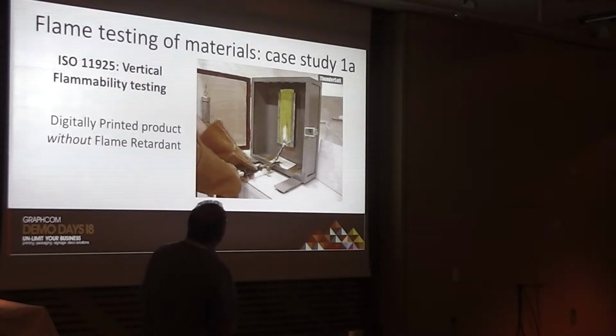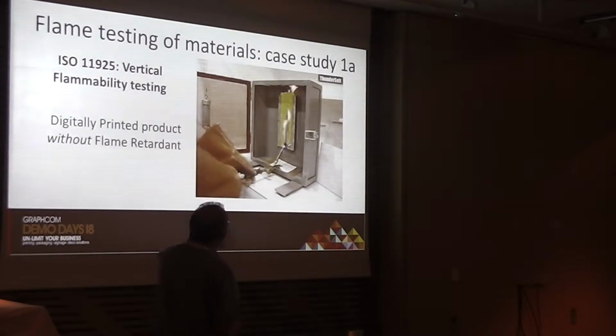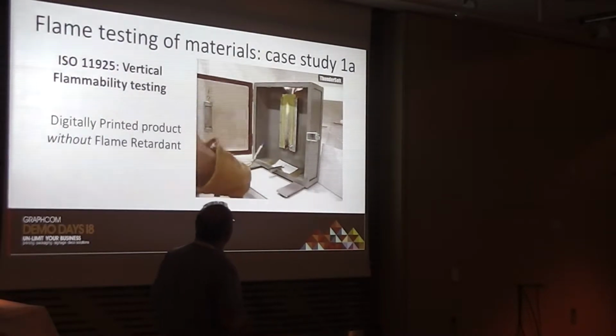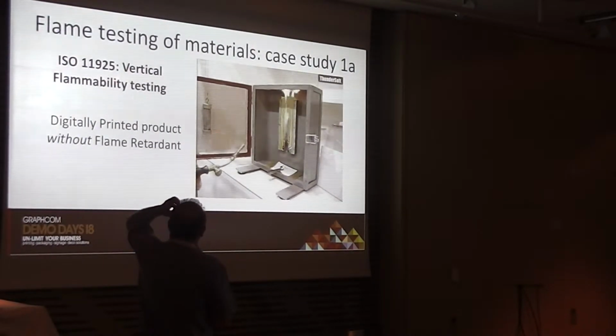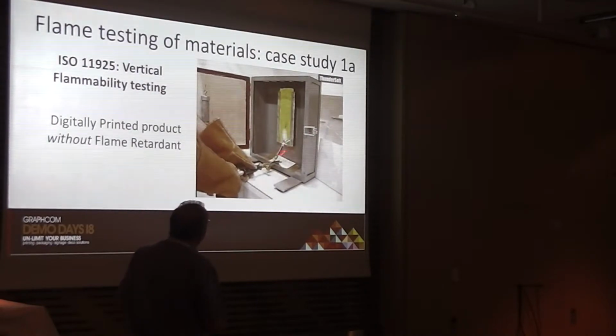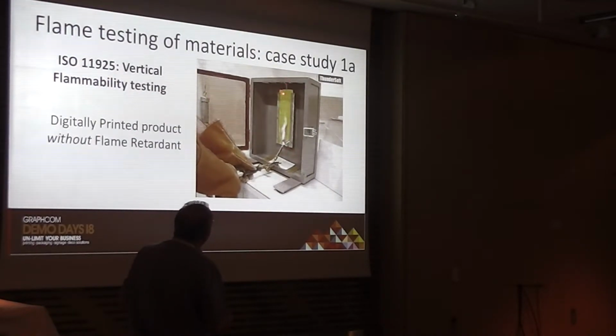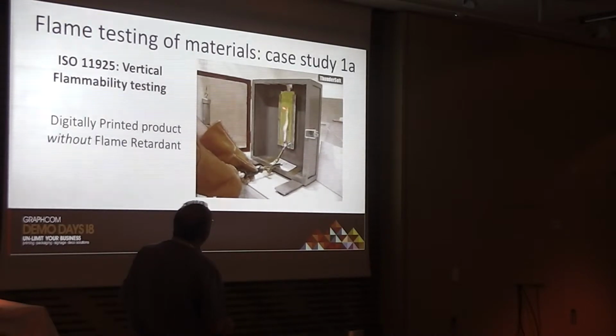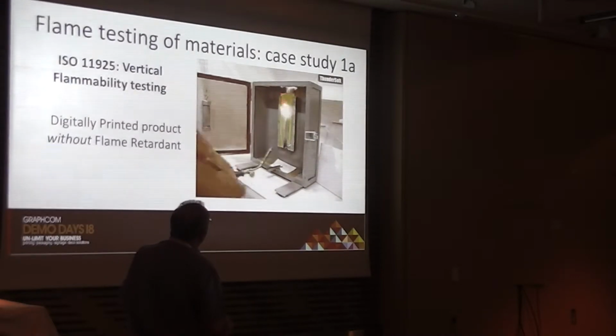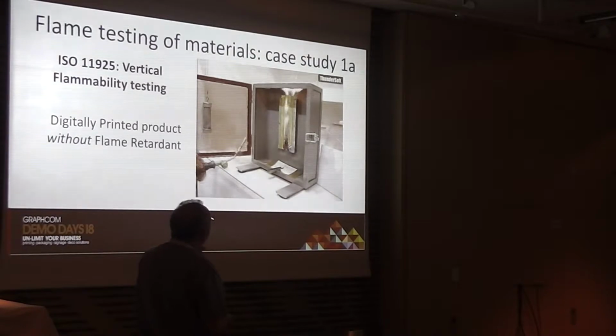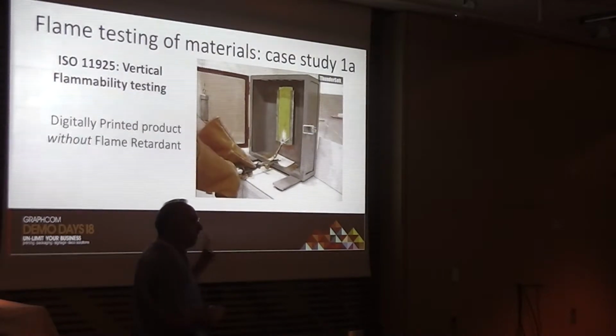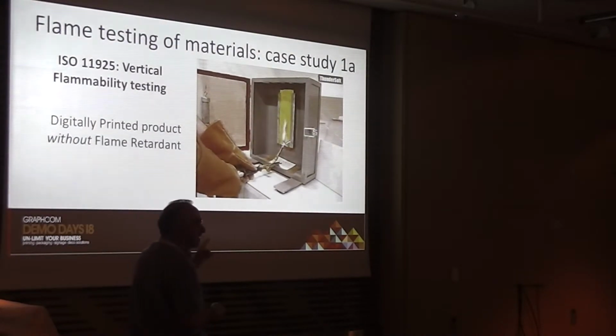This one here is a little GIF that shows it without flame retardant. It's actually a card that we did some work on some time ago. This is according to 11925. And you can see that the flame is already from behind and it's actually burning. There was a flame retardant on the material, but not on the final product, which was surprising. That's why they asked us to test it.